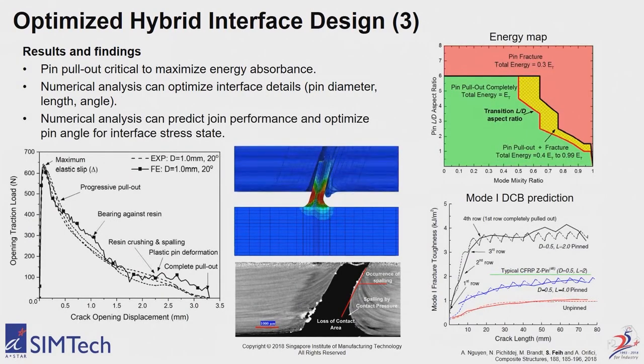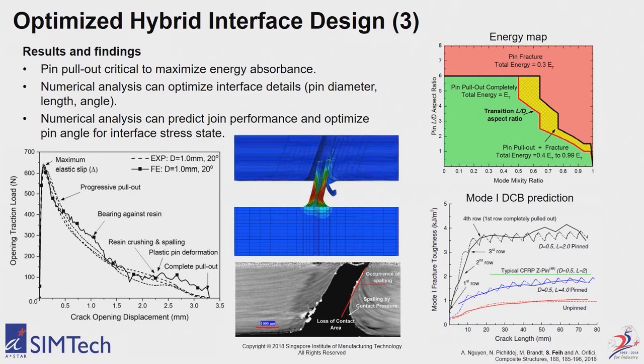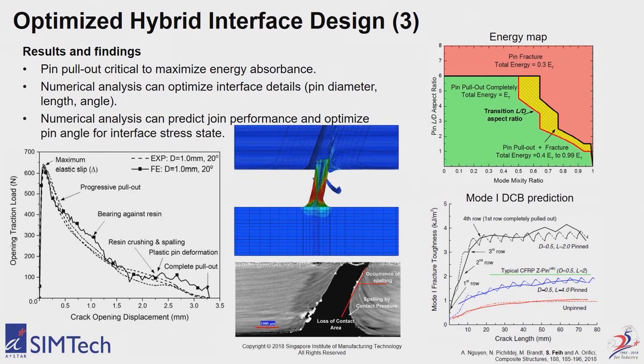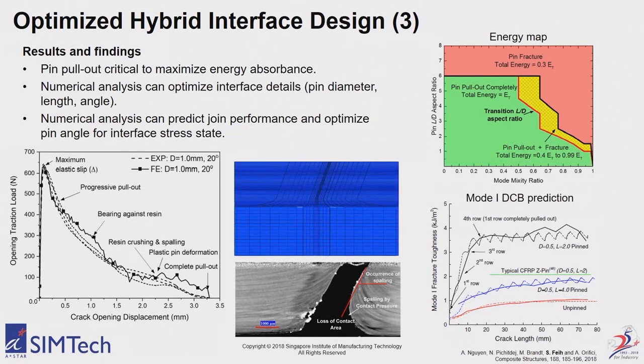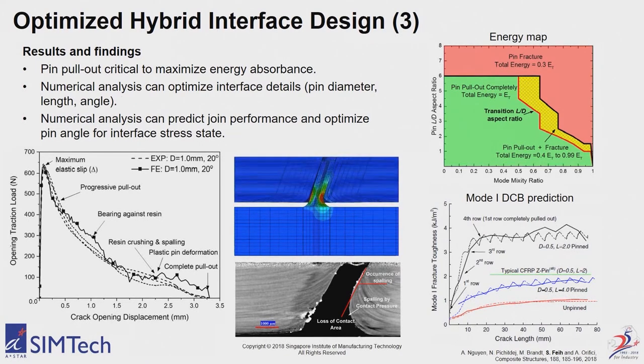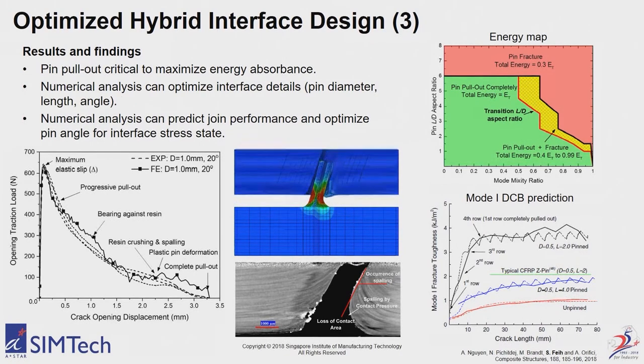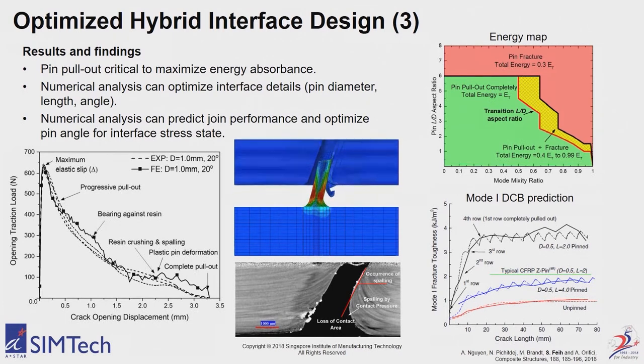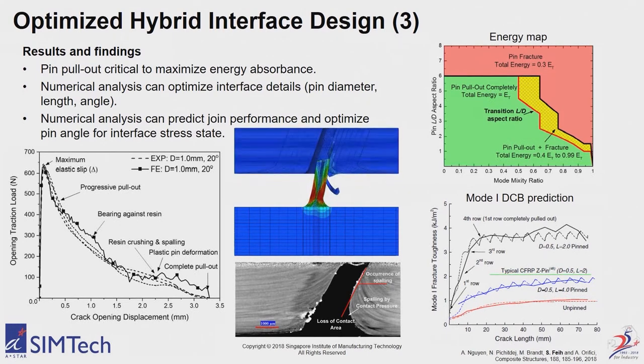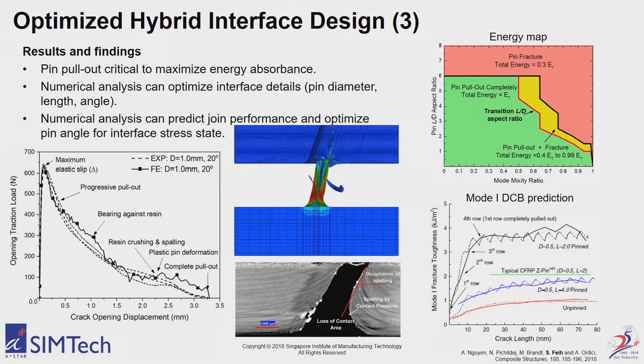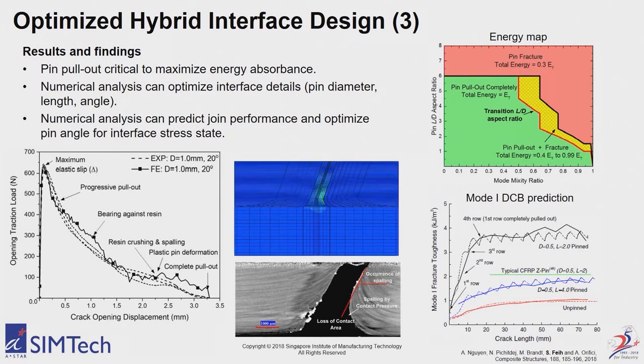And we can now use this to optimize the pin length and the pin diameter in our composite structure. We can see the maximum energy we get if we pull the pin out completely, and what we have to do to avoid pin fracture. So depending on the thickness of the composite, we can design the diameter of the pin, and we can design the